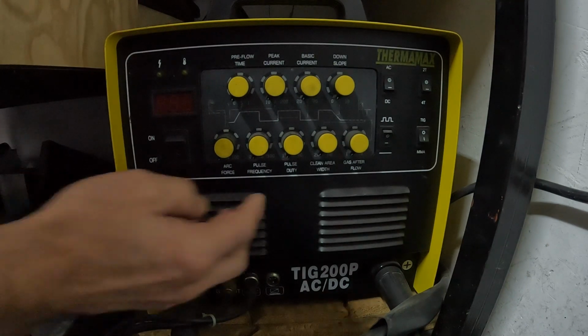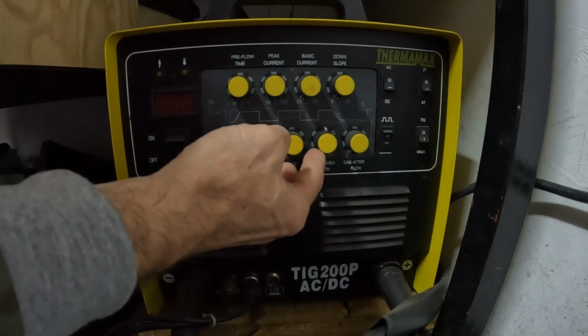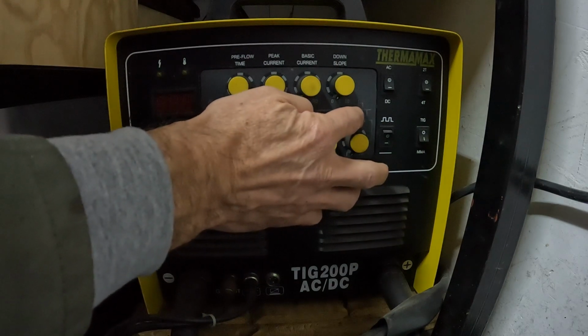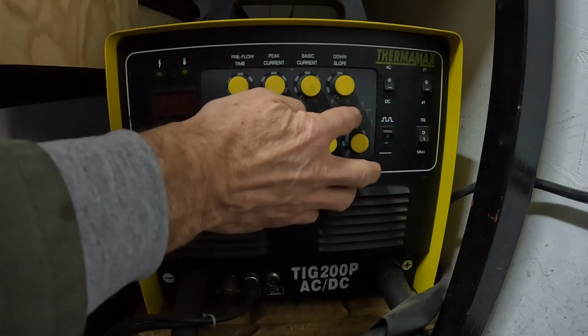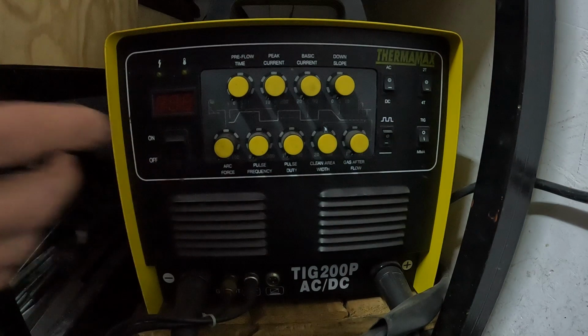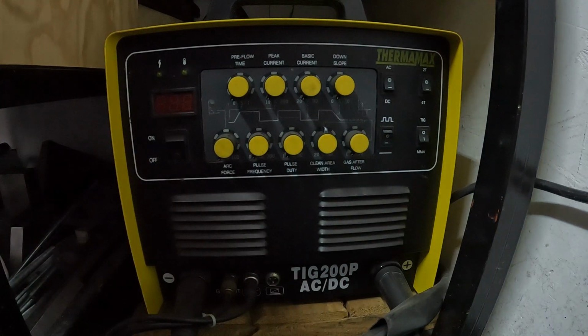So materials like aluminium with that oxide layer, you typically weld AC, and then that cleans that oxide layer off of the material. The cleaning area width is just how much distribution you have between the positive and the negative. The higher the cleaning width, the more energy you're taking away from the material, so the more that you're stripping the oxide off of the base material, but the more energy is going into the tungsten electrode, so the tungsten electrode gets hotter. That's why when you weld aluminium, you do need a thicker tungsten rod just to manage that extra heat transfer.